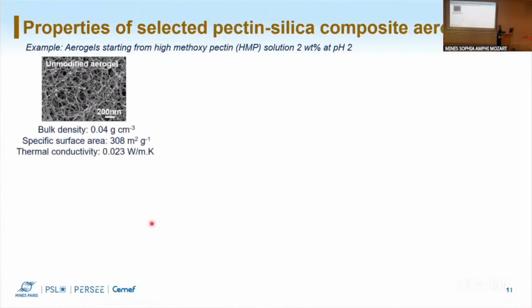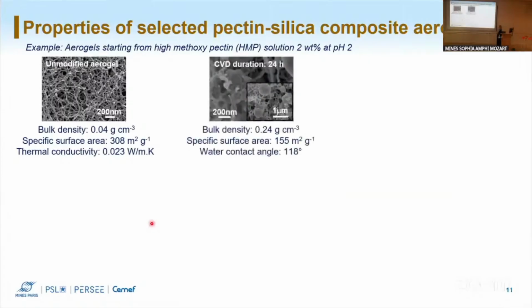Now, I will give you an example for one formulation, starting from a high methoxyl pectin solution of 2 wt% at pH 2. These are the properties of the neat material. We see low density, high specific surface area and low thermal conductivity. After 24 hours of chemical vapor deposition, we have a huge increase in bulk density and a decrease in surface area. However, we get hydrophobic materials, which was our goal.